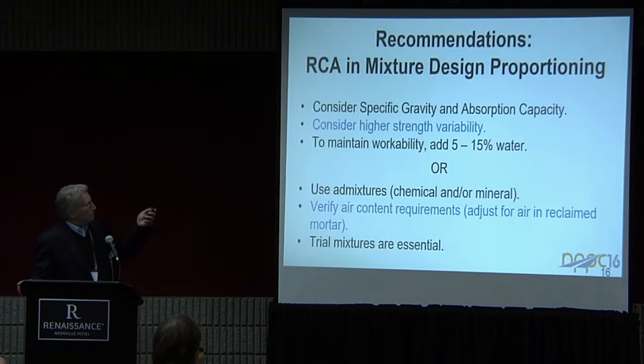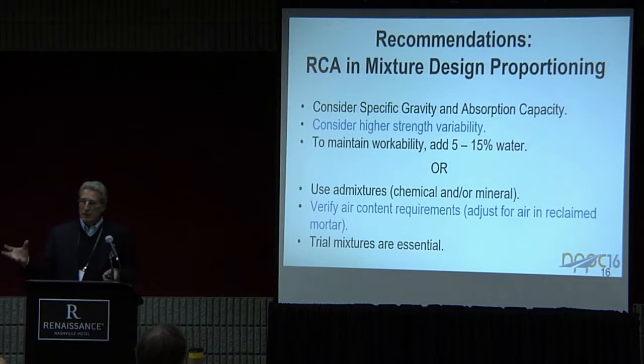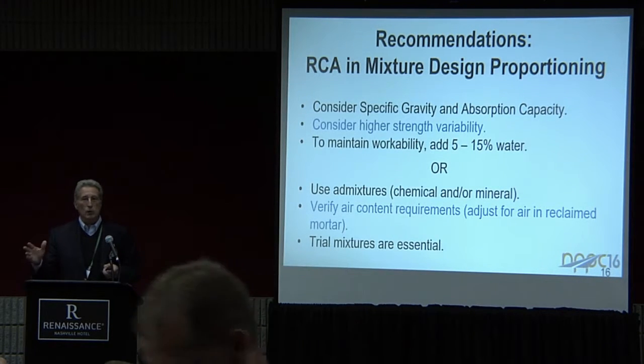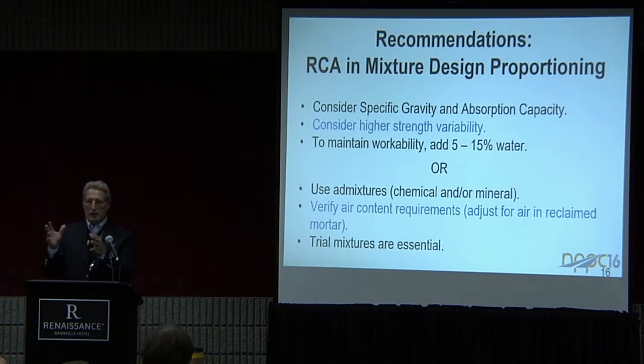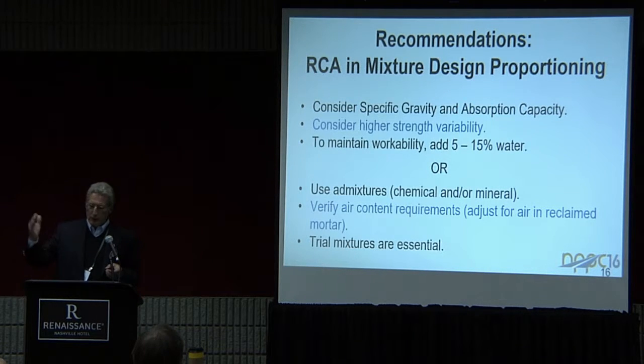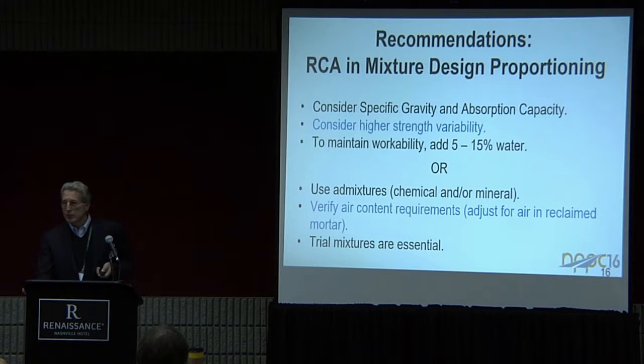In the proportioning, you've got a different specific gravity. You've got mortar that's clinging onto the aggregate particles, so your specific gravity is going to be lower. You can't batch things based on weight now. You've got to look at the volume and get a new weight for your aggregate when you're using recycled materials. And the absorption capacity will tend to be a little higher as well. May have a little more variable strength. And to maintain workability, chemical admixtures, mineral admixtures. Some folks like to just add a little bit of water, but if you add water, you've got to add cement too, because you don't want to change your water-cement ratio and make the mix less strong or less durable. So these are all different approaches for the proportioning.